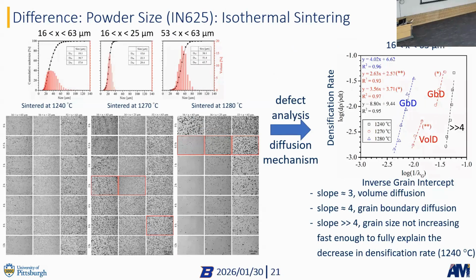So we wanted to learn more. Now we employed hundreds and hundreds of undergraduate students, right, to cut and polish tens of thousands of samples. No, not that many, but many, many samples for different size distributions of powder, different temperatures that we sintered at, and different times that we sintered at. Because what we want to learn here is what is actually the densification or sintering mechanism taking place during sintering, right? And with these different sintering times and temperatures, we could figure out that at the highest temperature we have grain boundary diffusion. At the intermediate temperature, we have volume diffusion and grain boundary diffusion. And at the lowest temperature, we have a situation where probably the defects are affecting the densification so much that there's no clear diffusion process or densification process present.